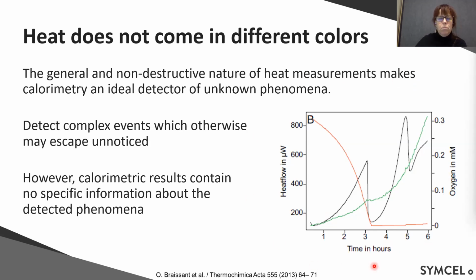Again, here is data from sometime in the 90s, I think, which was republished later on, where you have the black one, E. coli growth. It drops very suddenly. There were parallel measurements done by measuring the oxygen, and we can see at the time that the heat flow, the metabolic activity, goes down. We also see that the oxygen levels go down. So what we can see here, the growth starts again. And this is when it changed from respiration to fermentation. The green curve here, it's not on the scale, but this is OD measurements that goes on. So we can see there is a continuous growth of the data.